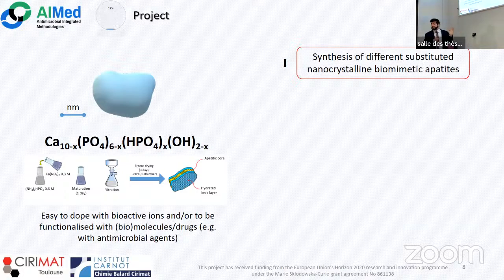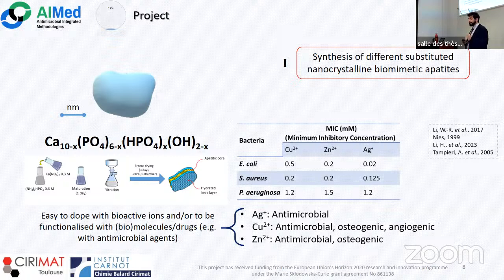It is a synthesis method that is extensively used in our lab here at the CIRIMAT, and it's a structure that is easy to dope and to substitute with bioactive ions in many sites, or to functionalize with biomolecules, enzymes, or antimicrobial agents. In our case, we will focus on the substitution with 3 metal ions, silver, copper, and zinc, that are all reported in the literature as being antimicrobial. Copper and zinc are also reported to be osteogenic, and copper is showing some interesting angiogenic properties.